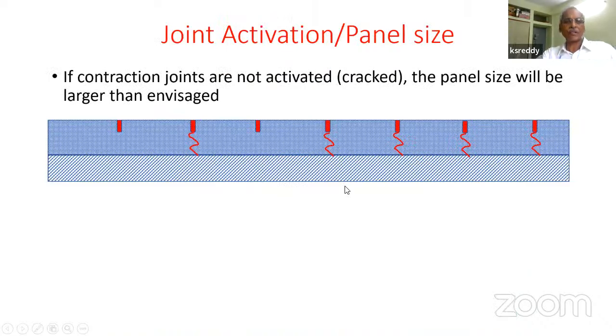Now there is a critical issue here. When you cut grooves and expect that a joint is formed and you have created a panel of this size, this is called joint activation. You cut a groove. Typically, this is cut to 1/4 to 1/3 depth of the slab. You weaken the slab there, and when it tries to contract or shrink, you expect a crack to form here. Right? For example, no crack forms here, no crack formed here, and maybe all these joints crack. We have maybe a 4.5 meter long slab here, 4.5, 4.5. This is a 9 meter slab.